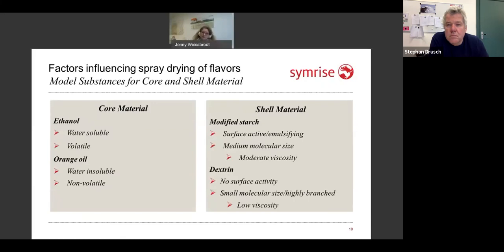Coming to the core material, what did I choose for this talk? I chose ethanol as a water-soluble volatile material, very easy to determine, and you can imagine it's difficult to keep inside this capsule or this drying droplet, because the molecular size is quite near to water. So if you can keep ethanol in, it would be even easier with most of the other water-soluble volatile components. And orange oil, a water-insoluble, non-volatile component, very sensitive, for example, to oxidation, and this is why it's used very much in the literature.